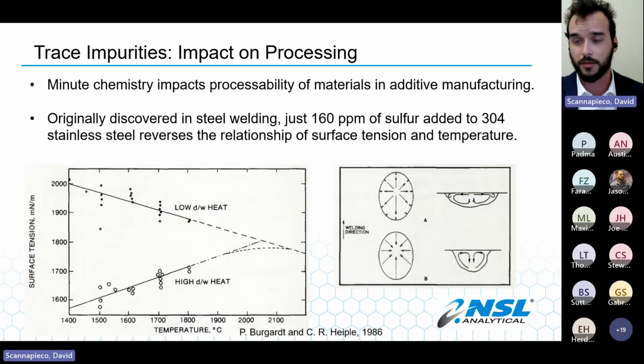So I talk about the importance of testing the chemical makeup of the powder to make sure that it can be reused in the right way. And that's mostly because even trace impurities in powders can cause a significant change to the processing parameters. So in this case, you have a 304 stainless steel, and with just an addition of 160 ppm of sulfur, you change the convexity of the liquid metal in the weld pool. And that goes from being a deep penetrating weld, which is more ideal in an additive case, to a shallow wide weld, which reduces remelting, potentially prevents layers from coming together, fusing the layers together.